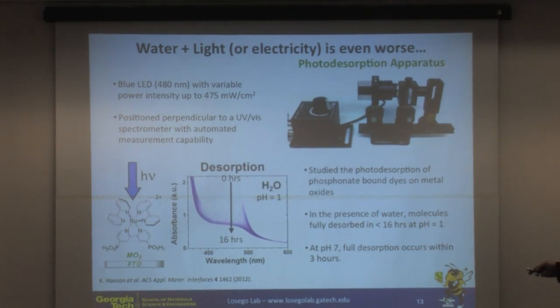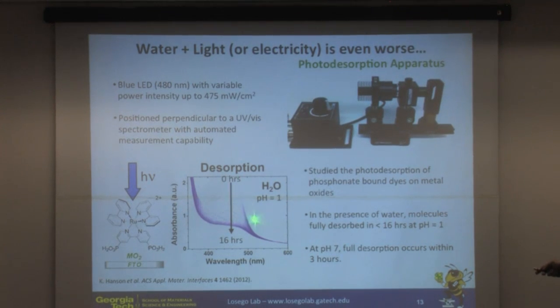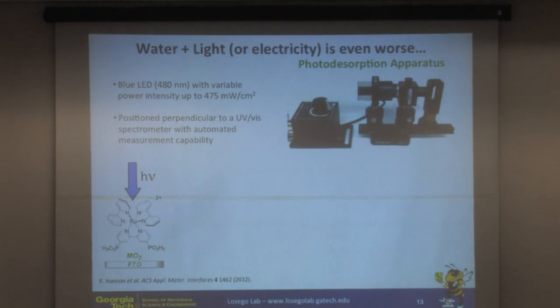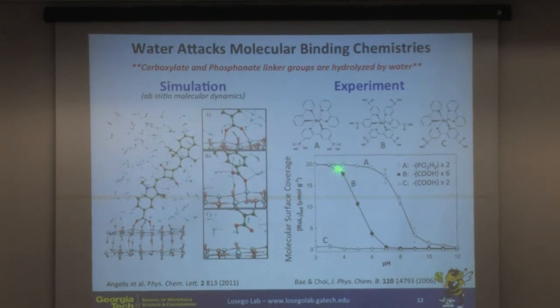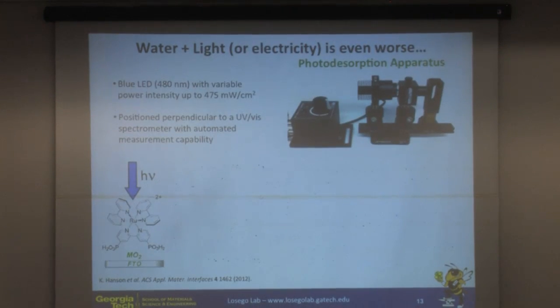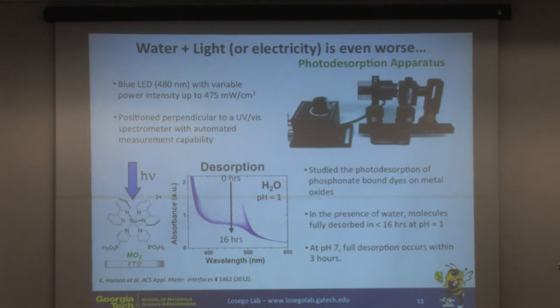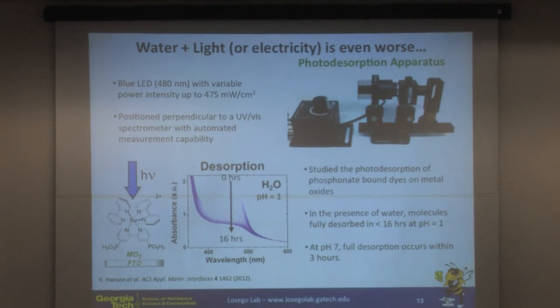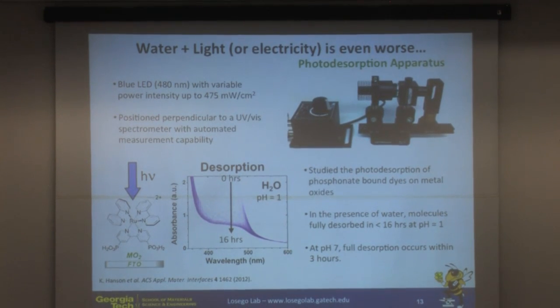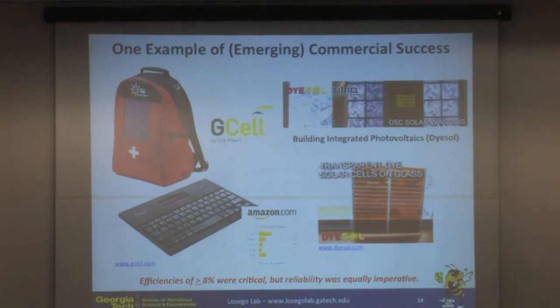And he tracked then using UV-vis how much dye was on a surface as a function of time, exposure to light, and we see rapid detachment within 16 hours. And so in this particular case, I believe we're at a very low pH, pH 1. So you'll see from the previous study that, you know, pH 1, we should be well attached to the surface, especially for a phosphonic acid. But here, as soon as we start to expose it to light, we lose and we detach these molecules within a period of less than 1 day. So this is really a challenge if we add additional stimuli to the system.